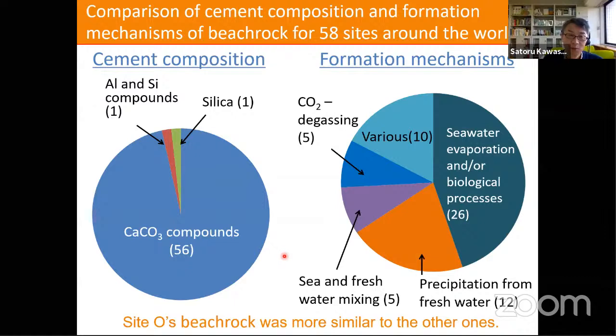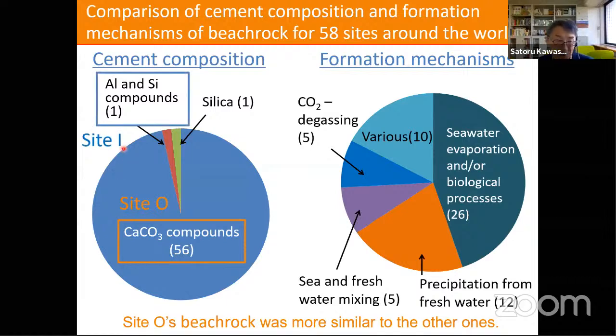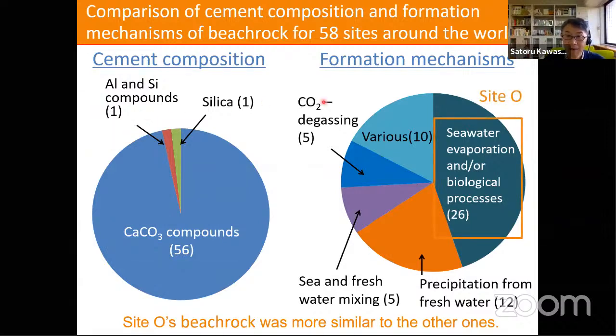Once again, comparison of cement composition and the formation mechanism of Beachrock, 58 sites in the world. The first one, cement composition: site O is mainly calcium carbonate compounds. Site I, which today, due to time limitation, I skipped, mainly consists of alumina and silica compounds. Regarding formation mechanism, site O is evaluated as a seawater evaporation and/or biological process, and site I is mainly formed by freshwater mixing.